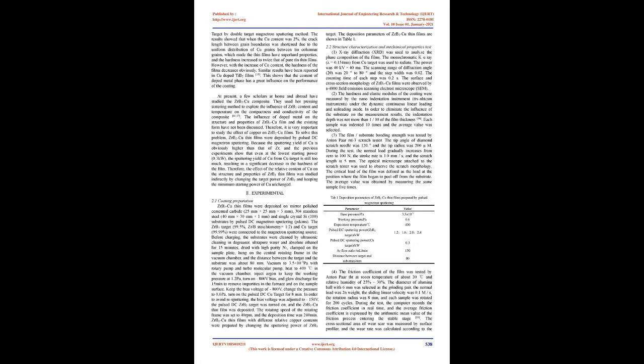To solve this problem, ZrB2-Cu thin films were deposited by pulsed DC magnetron sputtering. Because the sputtering yield of Cu is obviously higher than that of Zr, and previous experiments show that even at the lowest starting power, 0.3 kW, the sputtering yield of Cu from the Cu target is still too much, resulting in a significant decrease in the hardness of the film. Therefore, the effect of the relative content of Cu on the structure and properties of ZrB2 thin films was studied indirectly by changing the target power of ZrB2 and keeping the minimum starting power of Cu unchanged.